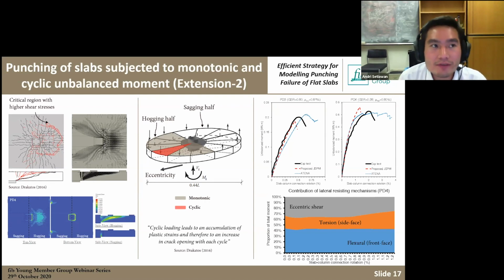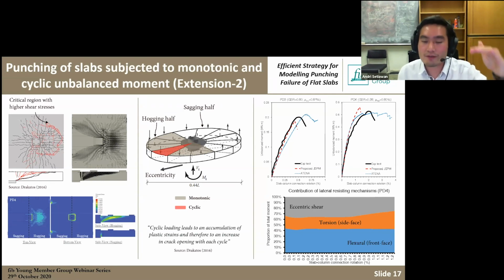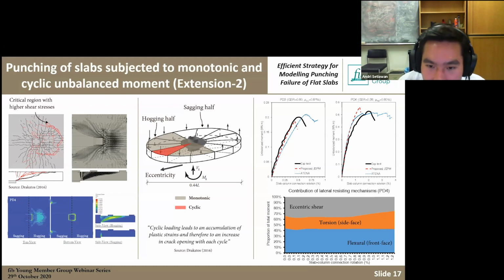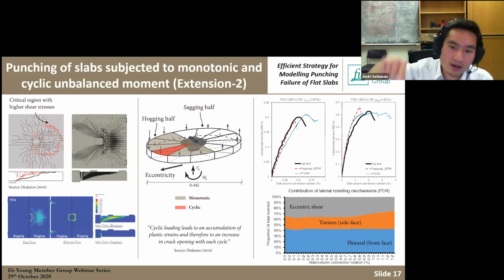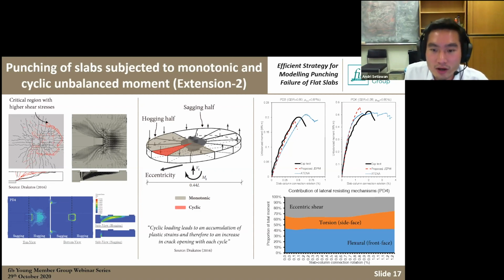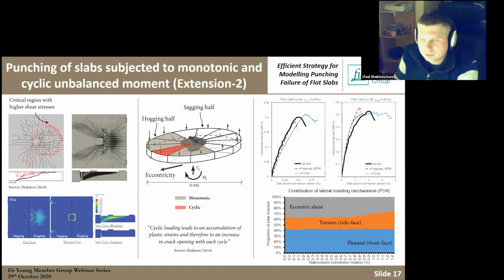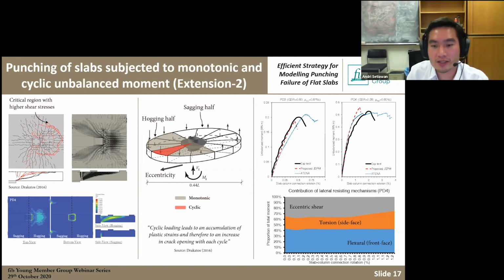So the shell itself is called a nonlinear layered shell. Basically, the difference between this shell and a conventional shell is that you discretize the shell into several layers, and each layer represents a plane stress element, where you have 2 by 2 gauge points on each layer. To get the moment, shear, axial force and everything, you integrate the stress from each gauge point on each layer through the thickness. I understand, so it's without sigma z. Yes, the out-of-plane stress is assumed to be negligible.